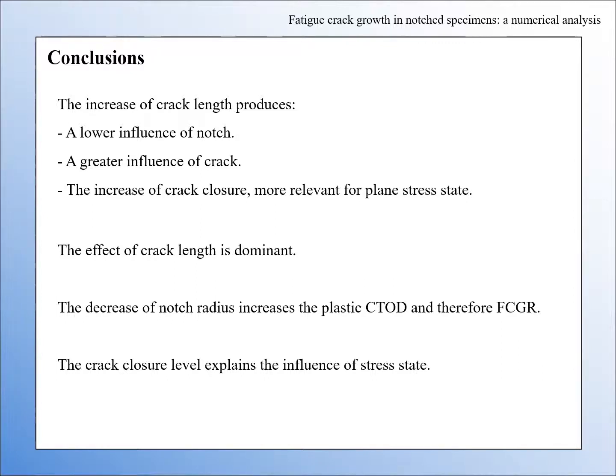However, the decrease of notch radius increases the plastic CTOD and therefore fatigue crack rate. Crack closure level explains the influence of stress state.